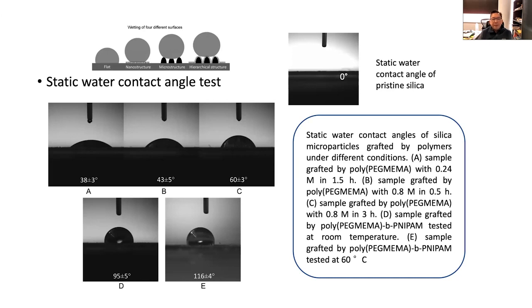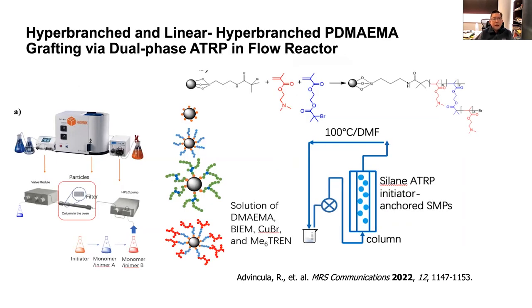The polyNIPAM is the last monomer, which is temperature sensitive. So using the lower critical solution temperature, or LCST, when we heat up, the sample becomes more hydrophobic. In this last example, we then utilize this system to graft hyperbranched polymers.